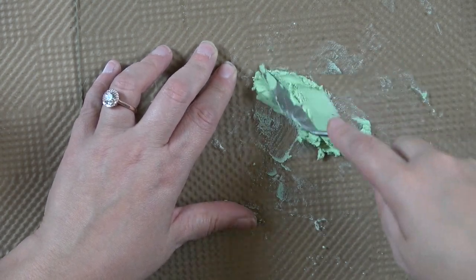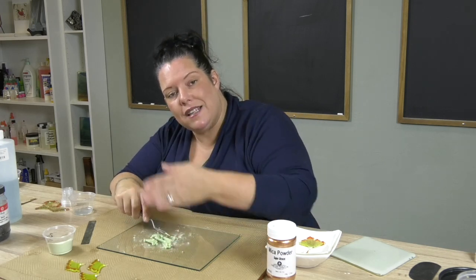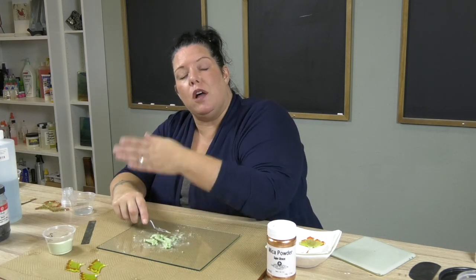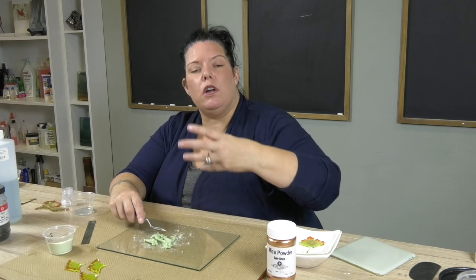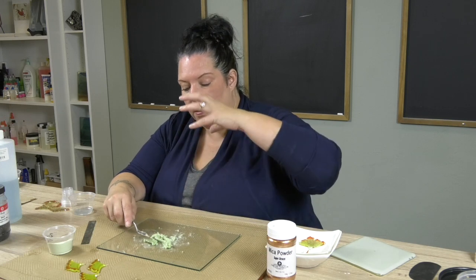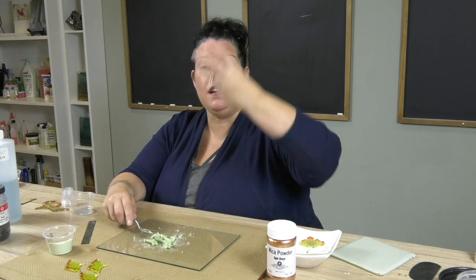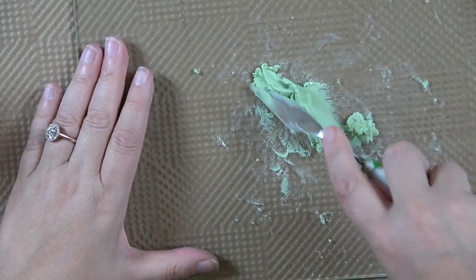It's stiffer, all right? We want it to be stiffer, which means it's more powder, less gel, because when we put this in the kiln and make the texture, we're going low. I can't recall the schedule. It's in your packet. I've done so many schedules this week. But it's going low. If you go too high, it's going to melt down into the glass. The beauty of this technique is retaining the texture, okay? Almost like a pâte de verre.